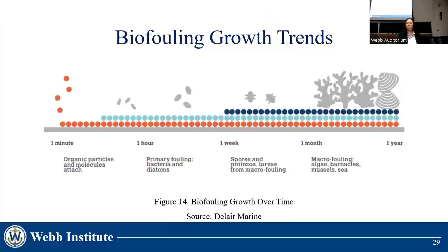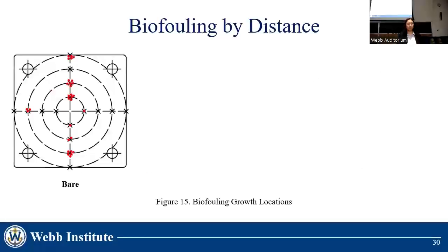The growth types observed were in line with the previously discussed biofouling trends, with bacteria and diatom growth occurring over the truncated 1-week window. A longer testing window would allow for more varied fouling to occur. Above, the red dots denote microbiology identified on the test plates, recorded at their respective locations.